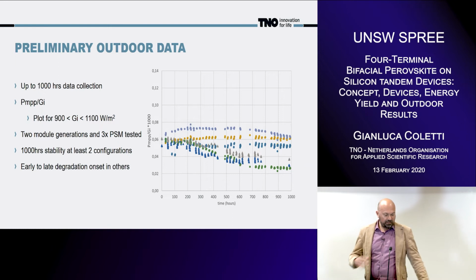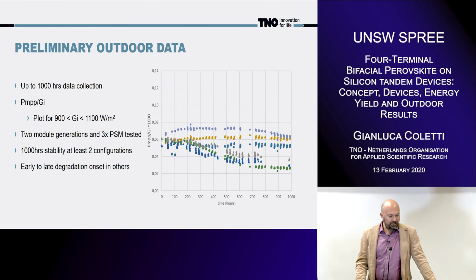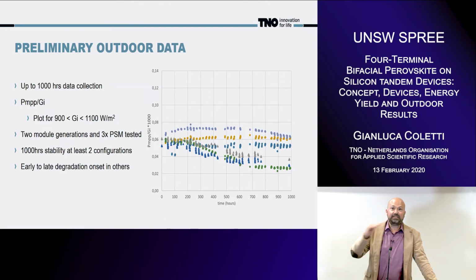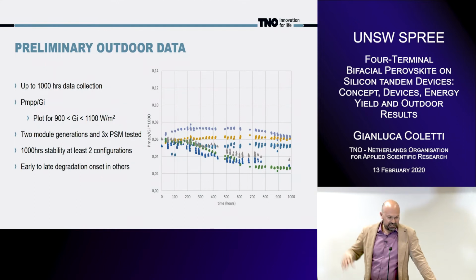So we went further. We measured for a longer time, up to 1,000 hours of data collection. Here I report something different. This is the power over the irradiance, but I plot only the irradiance values between 900 and 1100 watt per square meter. So they give an indication of how stable the performance of the device is.